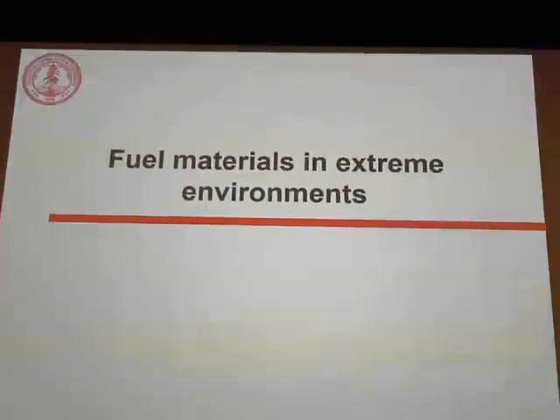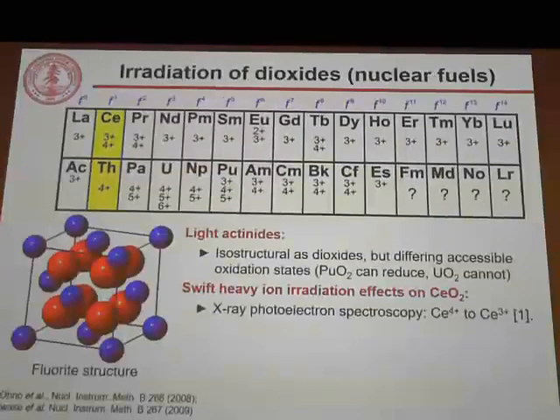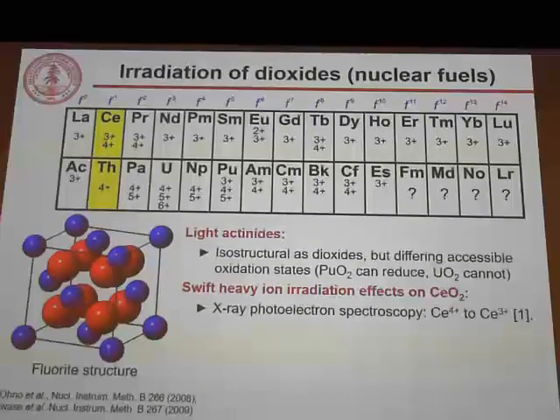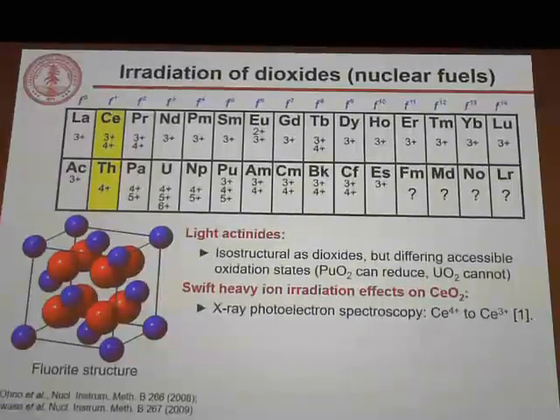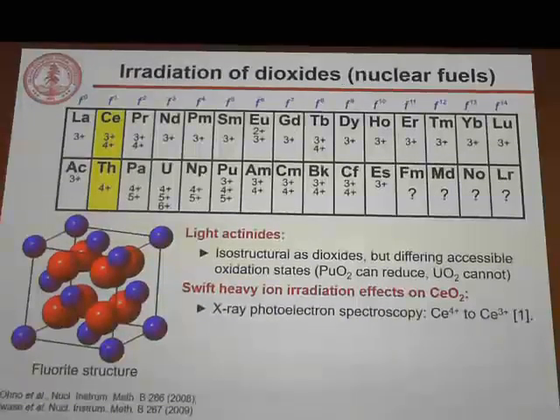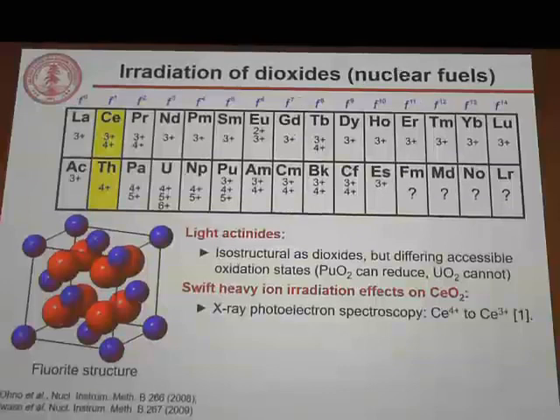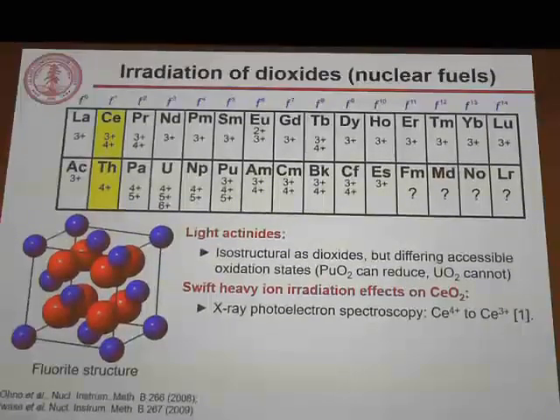So I'll start by talking about some work I've done on fuel materials in extreme environments. And of course, for fuels, it's the dioxides that we're really interested in, particularly dioxides of the light actinides, things like thorium, uranium, plutonium, of course. These materials, as dioxides, are all isostructural. They all adopt this fluorite structure I show in the lower left corner. However, they have very different accessible oxidation states. So in this F block that I show at the top of the slide, below each element, I have the oxidation states that it commonly adopts in an oxide. And you can see that what's really unique among the light actinides from actinium to americium is that this changes dramatically as we move from one to the next.